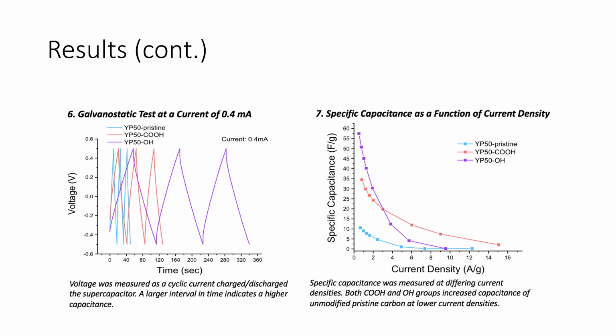In summary, my experiment supports my hypothesis that the functionalization of carbon electrodes with carboxyl or alcohol groups can increase the energy density of supercapacitors. However, the benefit in energy density is not as pronounced at high voltage scan rates or high current densities.